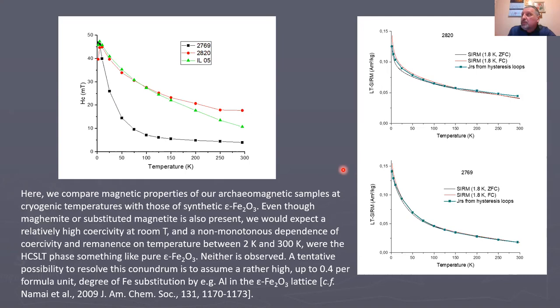One possible way to bring this data to close agreement is to suppose that epsilon phase in archaeological samples is highly substituted, but this of course needs further investigation.